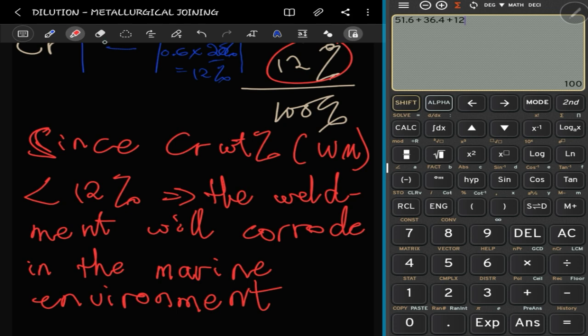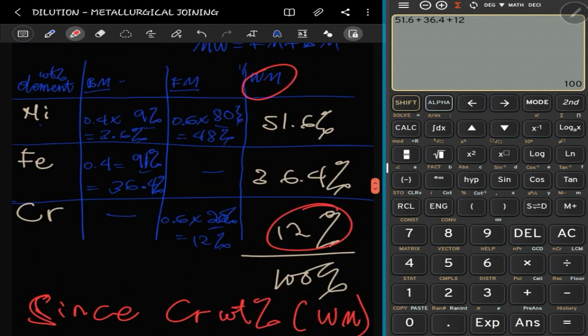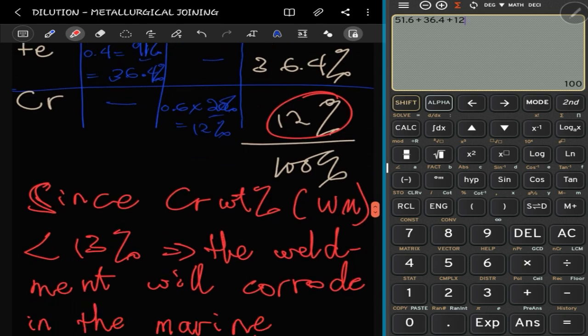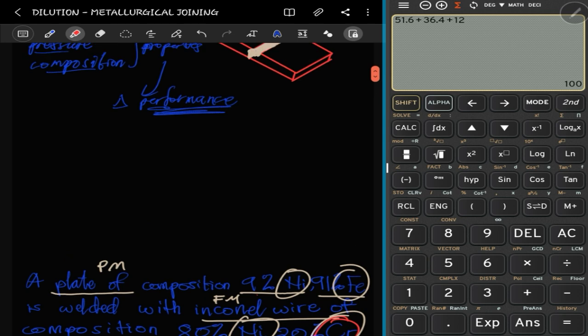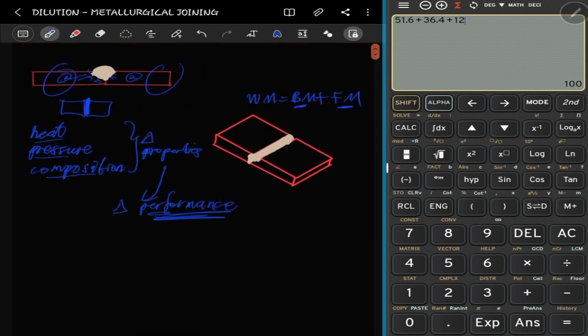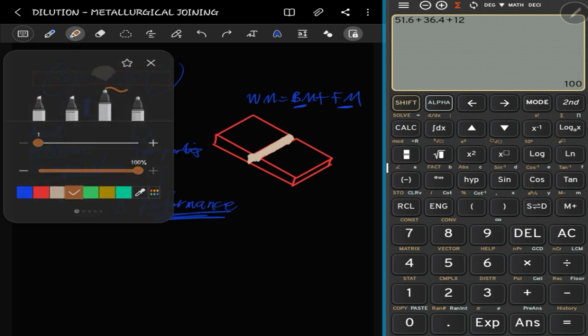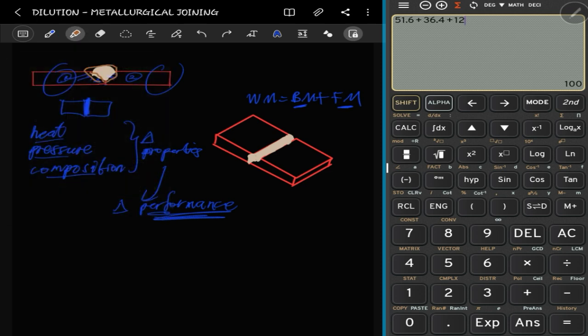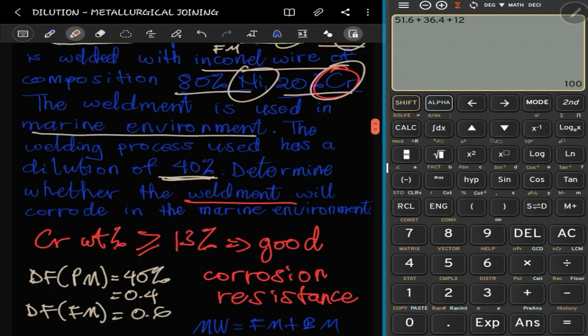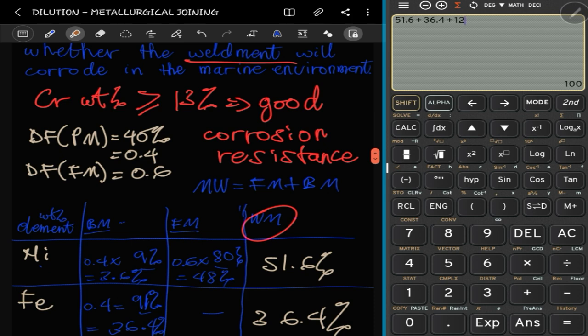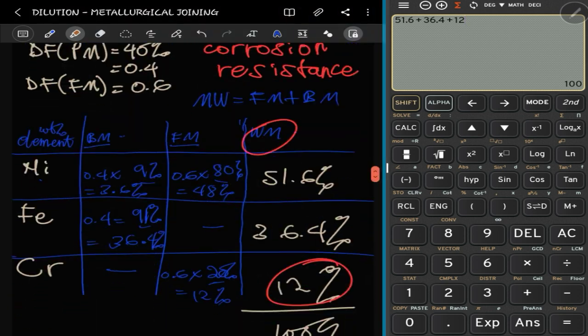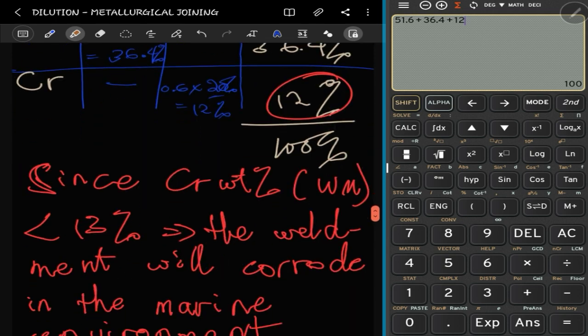So this shows us that since the amount that we are getting here, sorry, this should be 13. This should be 13. Since we have 12 for the chromium in the weld metal, and since this 12 is less than the 13, the weldment, which we've identified to be this side, this one right here, let me use a different color. We've been able to identify that this weldment here will corrode in the marine environment, right? This weldment will corrode in the marine environment. So weldment, weld bead, weld metal, they are the same. So this shows us that the weldment will corrode in marine environment. All right.